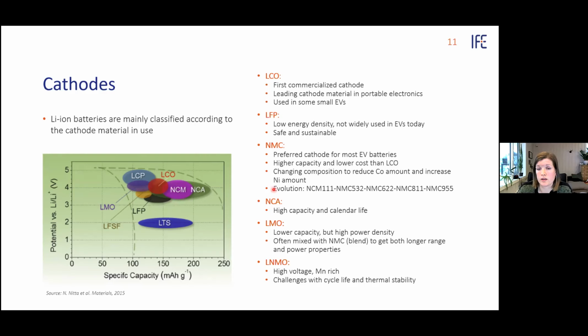It started with NMC 111, meaning that nickel, cobalt, and manganese all had the same composition, towards NMC 532 and then 622, and now most producers are going for 811. But we also see the next ones trying to prepare for 955, so meaning 9.5.5, to even further reduce cobalt and increase nickel. This is expected to be on the market closer to 2030, as there's still a lot of research on this.